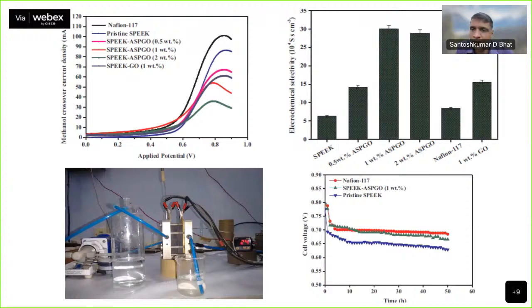So these are some of the important characterizations we do. Before we do the direct methanol fuel cell IV characteristics, we also do the methanol crossover through linear sweep, where we measure the methanol oxidation current, where we again notice which composite membranes can tolerate this, and how the methanol oxidation current can be minimized at the cathode. So we understand this by doing the linear sweep. And then we also do the study with respect to electrochemical selectivity, where we balance the conductivity and permeability. So this is very, very critical to understand the overall durability of the system.